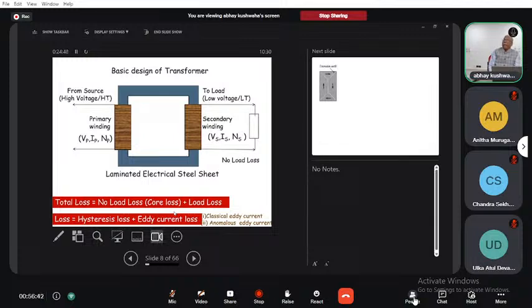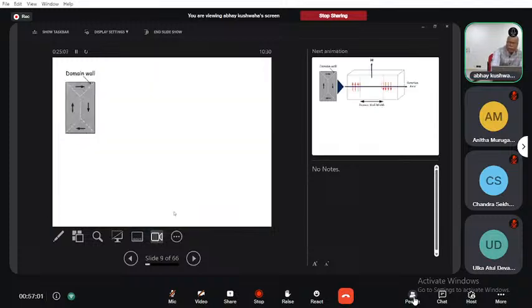But if we have a better material which has less eddy current loss, so total losses will be reduced. So again, eddy current loss has two components, which are called the classical eddy current loss and the anomalous eddy current loss. Now let us think quickly about this soft magnetic material or any magnetic materials. It has domains, and its domains are oriented in such a way. The domains are in the spontaneous magnetization state, and they are oriented in such a way that from the outside, though no field is applied, there is no net moment in these materials.